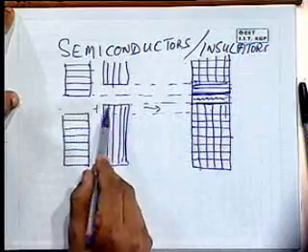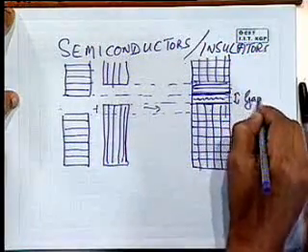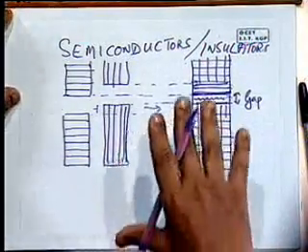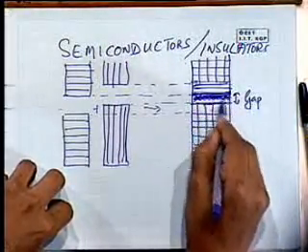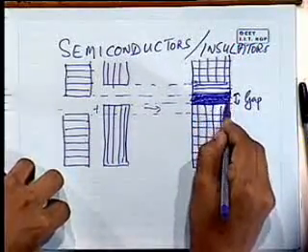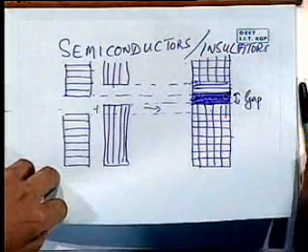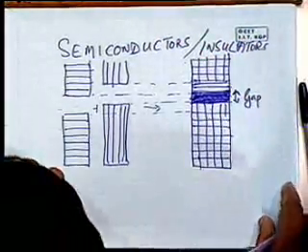In other words, the overlapping of all these leads to a gap that is formed in the overall band picture. And the actual magnitude of this gap will determine whether it's a semiconductor or an insulator. So the basic difference is that in all of these cases there are E versus K discontinuities, certain forbidden values of K that the electron cannot acquire, except that in metals, because of the overlap in different directions, the electron is able to move in some other direction and acquire that K value and correspondingly that energy value, whereas in semiconductors and insulators we end up with a forbidden area due to the overall picture having some gap, and the magnitude of the gap gives us the value for a particular semiconductor or insulator.